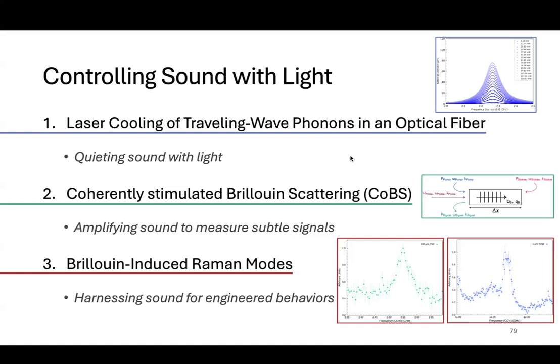Line width provides a direct window into dissipation rate, because the shorter the phonon exists, the faster it has been dissipated, right? And a more localized in time phonon offers a wider spread in energy, via the time-energy uncertainty principle, which is ultimately a mathematical consequence of Fourier analysis.